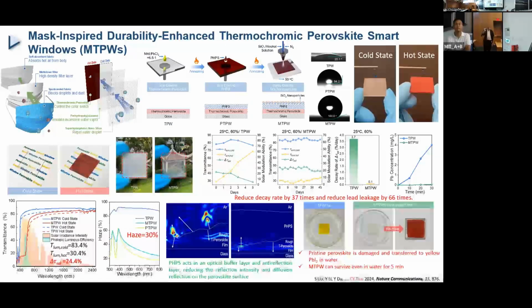So in this way, we put up 2 extra coatings. One is PHPS coating. The other one on top of the PHPS coating is silicon dioxide nanoparticles. So in this way, we can achieve a super hydrophobic surface with a contact angle over 160 degrees. And you can see that no matter in the cold state or hot state, the water droplet totally repels. A small amount of water vapor can penetrate into the perovskite to trigger the thermochromics.